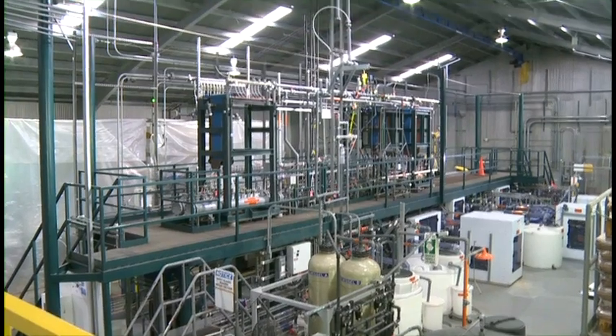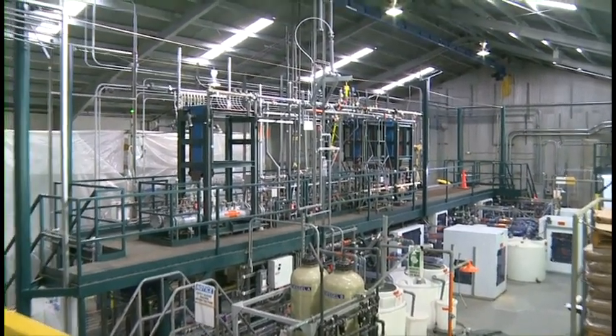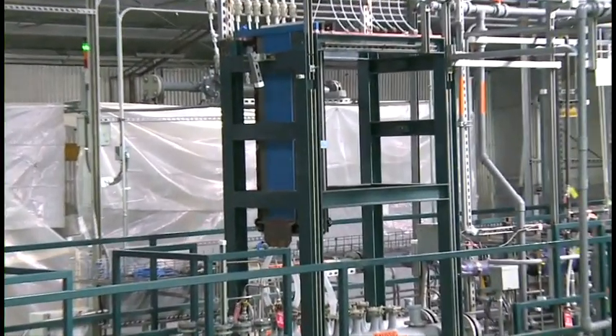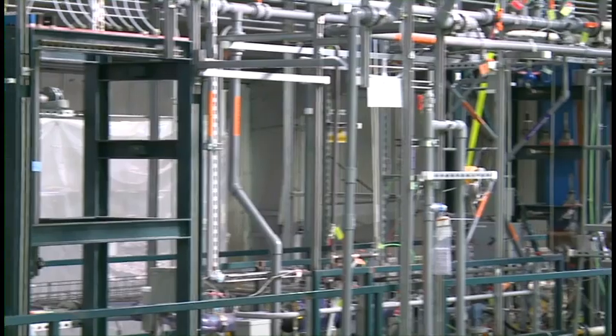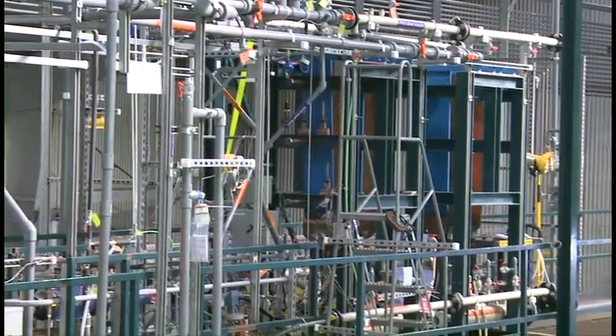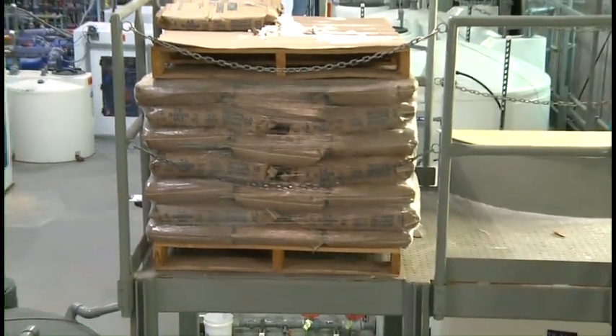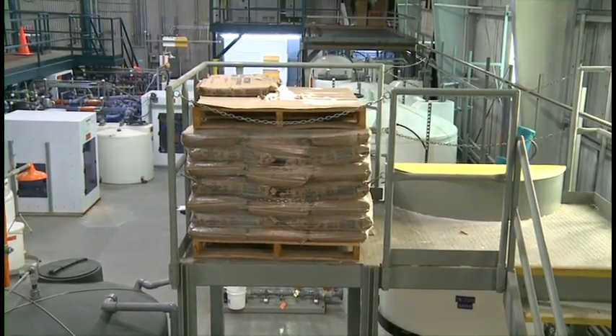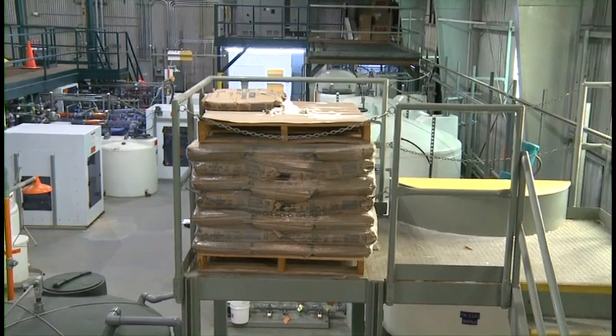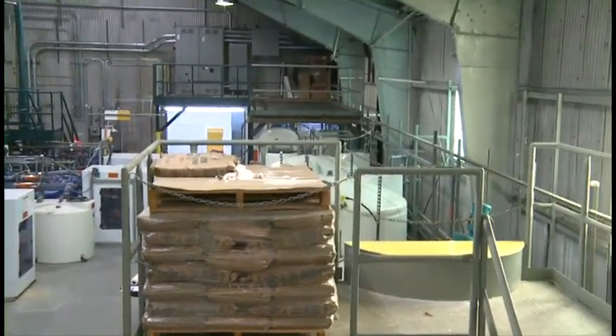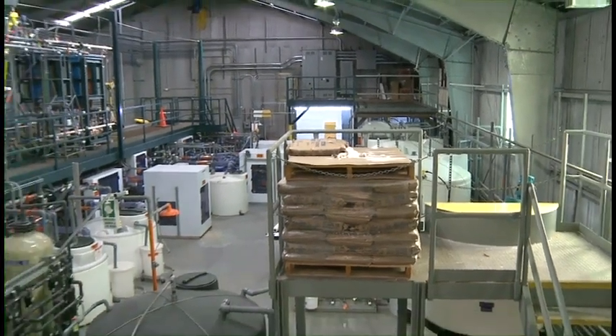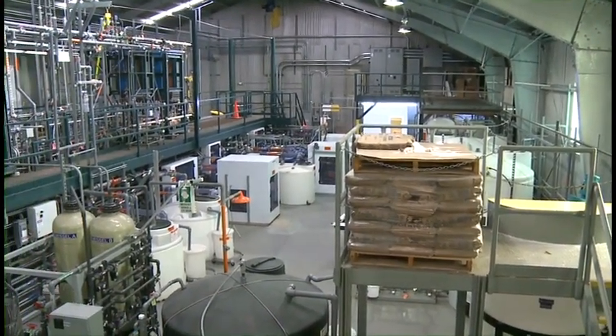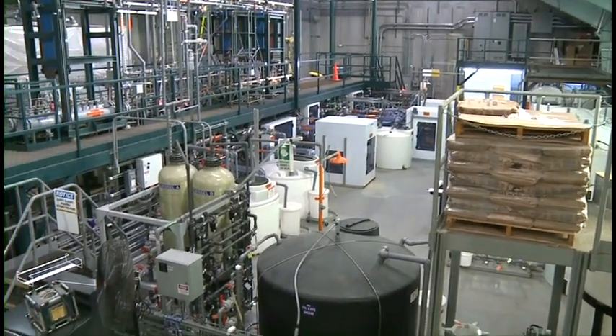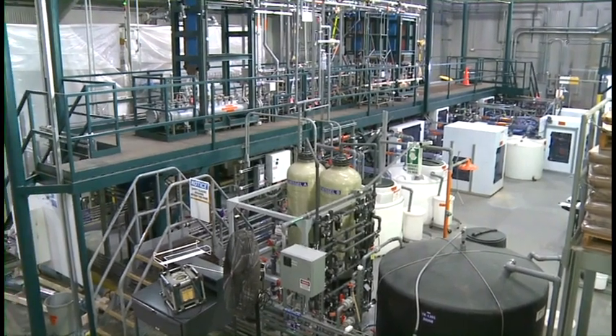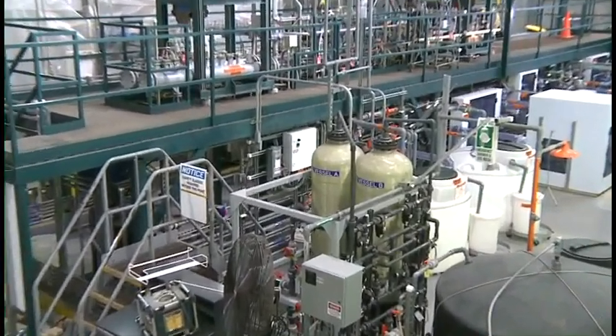So what you're seeing here is the electrochemical cells that we use to generate that alkalinity. The blue devices are a series of different, what we call cells, which are similar to batteries, except very large scale batteries, that generate this alkalinity. You can see what we start with right here is salt. So you're just taking salt and water and splitting it using electricity to make sodium hydroxide and an acid such as hydrochloric acid. And so the process you're seeing here and below is all just the processing of the salt. We take the water, clean up the water, make sure that it's very clean before it goes into the cell. But this is really one of the key enabling technologies that allows us to do this process economically by being able to generate alkalinity with low energy.